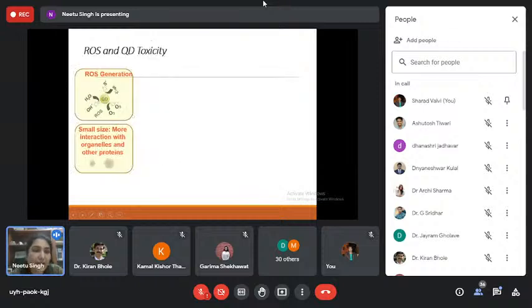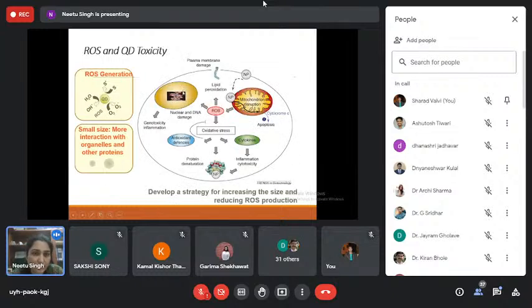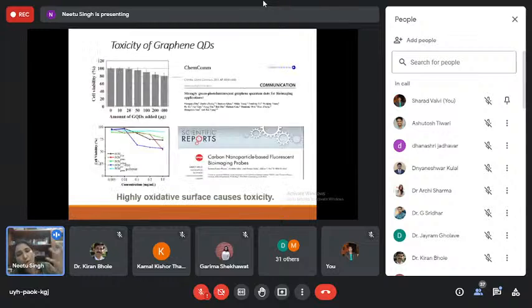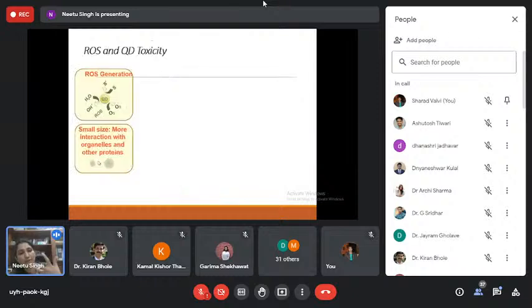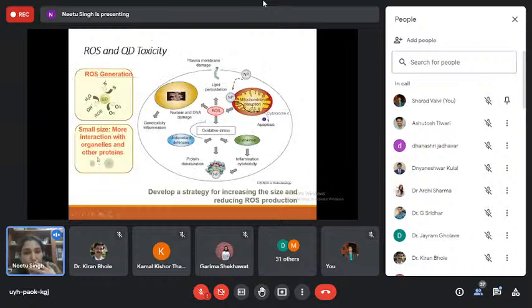Why is that happening? Again, I told you there could be ROS generation, and the toxicity is probably because of the ROS and because of the small size. Because remember, for quantum dots, you want them to be smaller, because otherwise if you make them bigger, you lose the quantum effect, you lose the fluorescent property of that particle. Okay, so you have your ROS generation, you have your oxidative stress which causes damage and things like that.